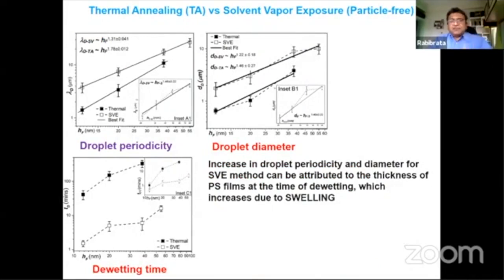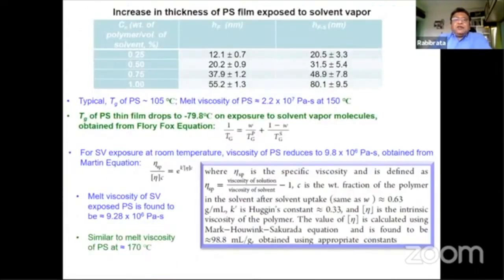We plotted some of these usual variations of the periodicity, droplet diameter, time of dewetting, and this is very interesting. You can see that there is an orders of magnitude difference in the times. So solvent vapor induced dewetting time was of the order of minutes to 10 minutes. Instead, in thermal annealing, it was of the order of days. So anyway, we sort of thought that we had discovered nothing new. We just quantified it. And then we looked into some little bit more critical measurements.